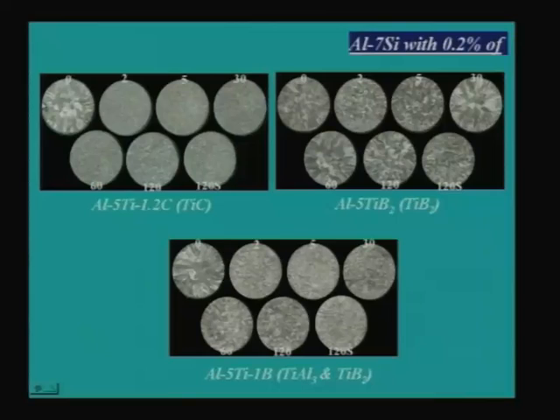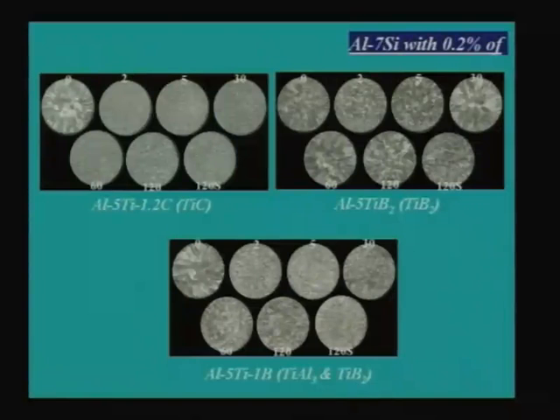Here again, TiC, the titanium carbide, is much stronger than titanium silicide. The interaction parameter is much stronger, because of which the affinity is high. Though if you hold it for a very long period there is some reaction of silicon with TiC, particularly at short holding time you can see that here you get very good grain refinement. And if you add TiB2 alone, you do not get that. And if you add a conventional alloy, which is 5 titanium 1 boron containing TiAl3 and TiB2, again you see you do not get as good grain refinement as you get here. So this is one important thing, that TiC is a good grain refiner not only for pure aluminum but also for aluminum alloys which have poisoning elements.